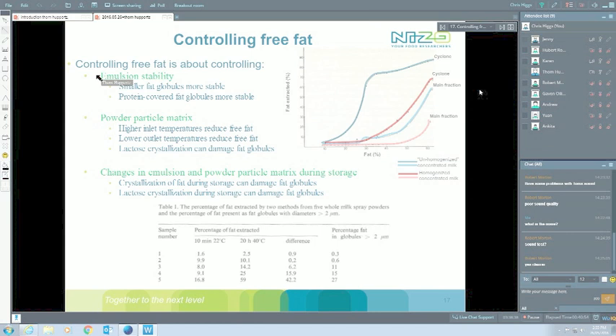The other aspect that we see is that even during storage, even if we make powders with low free fat, it can get worse over time in case you get lactose crystallization. I mean, you get your lactose crystals growing in your powders, bit by bit, they start damaging fat globules, actually start squeezing the fat out, and we start getting it onto the surface.